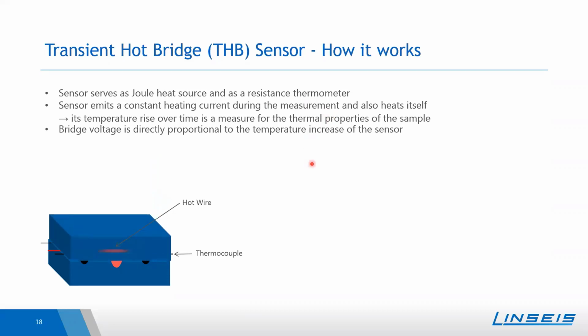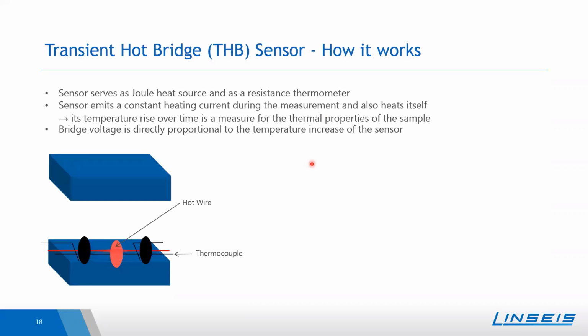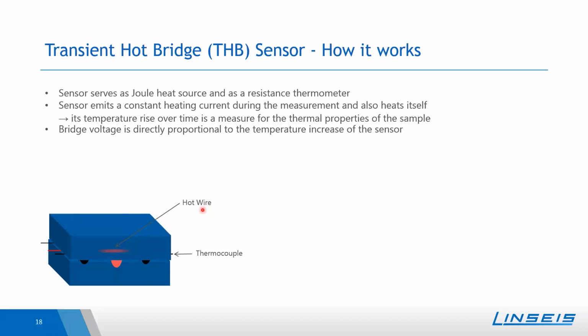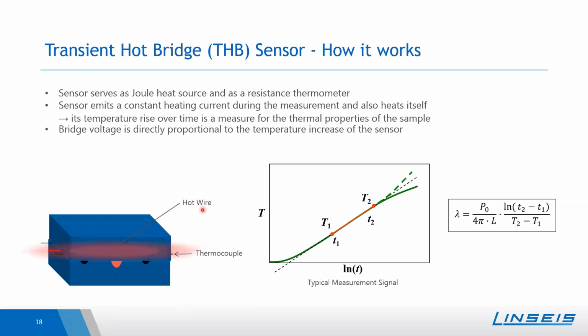So what one does is one embeds the sensor within 2 sample pieces. So here you see the illustration. This is more or less the sensor, or simplified, it is a hot wire. And there is the thermocouple, and during the measurement, the sample and the sensor will be heated, and one will get a temperature increase with time. Based on that, one is then able to determine the thermal conductivity.